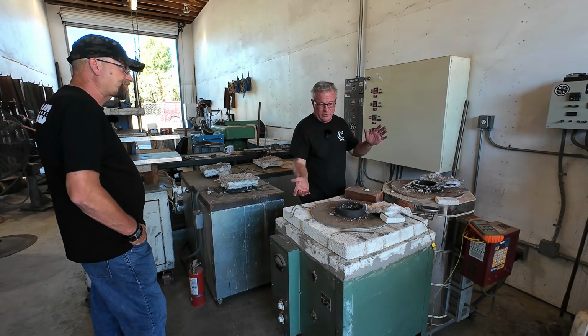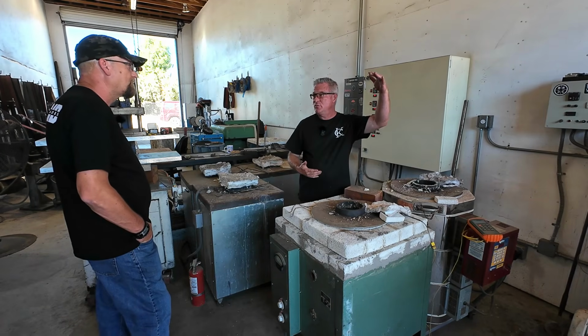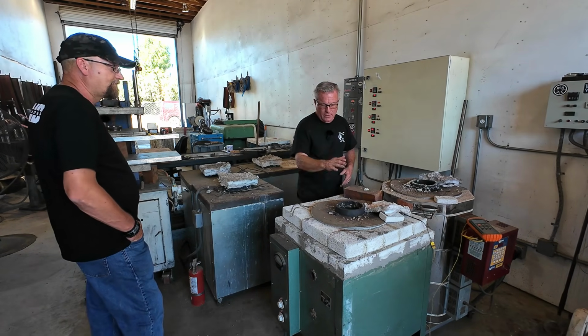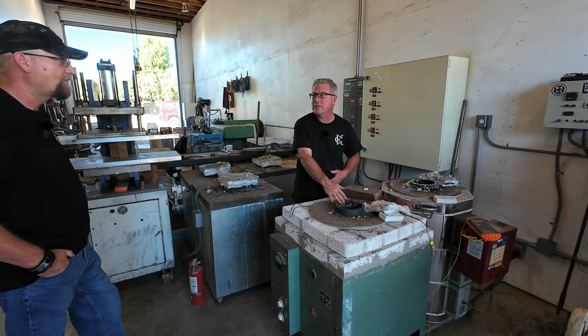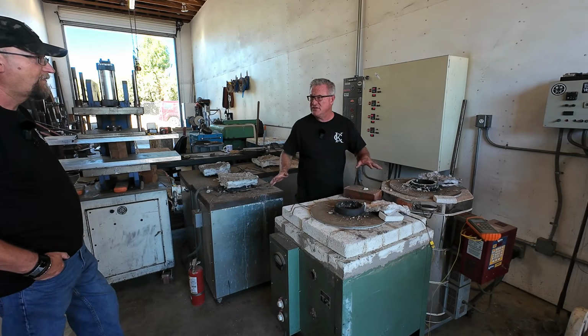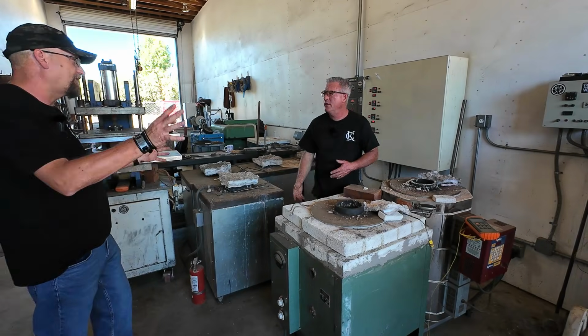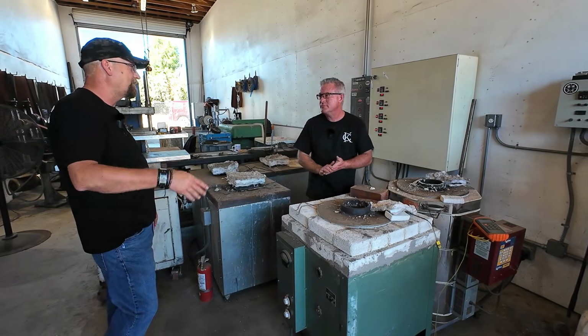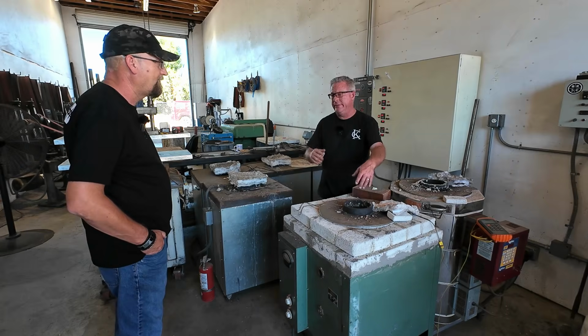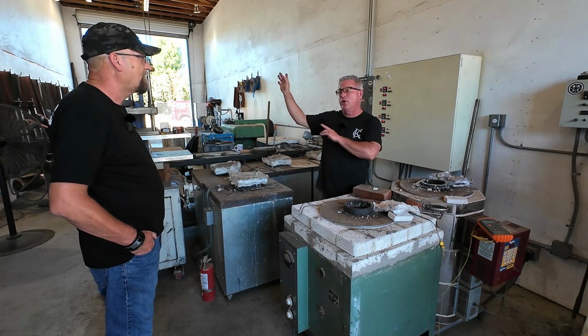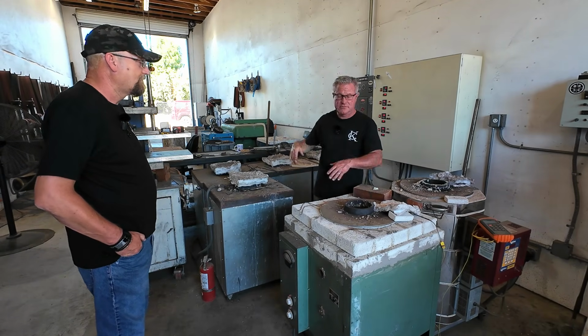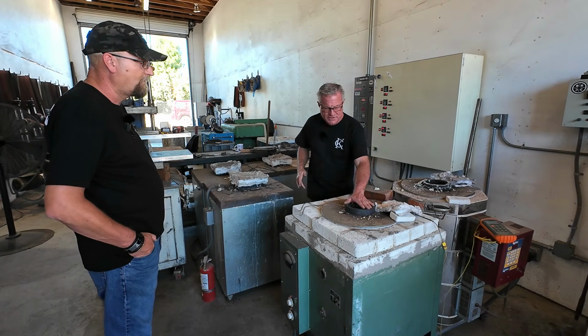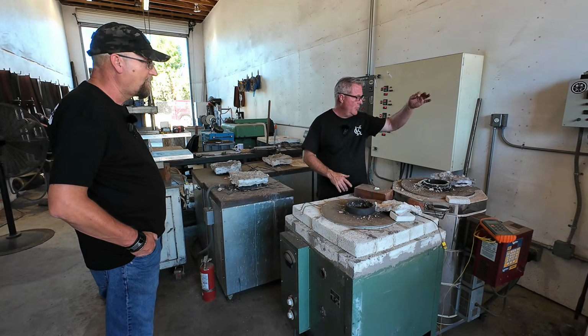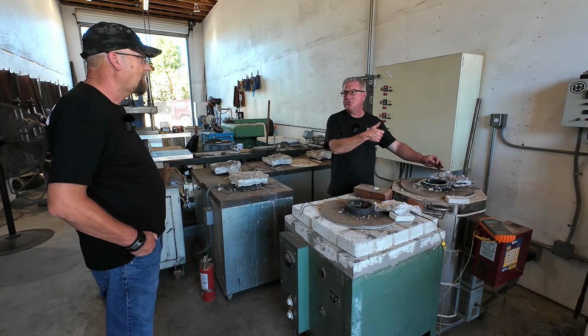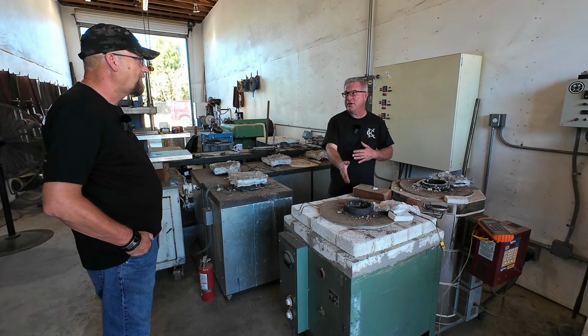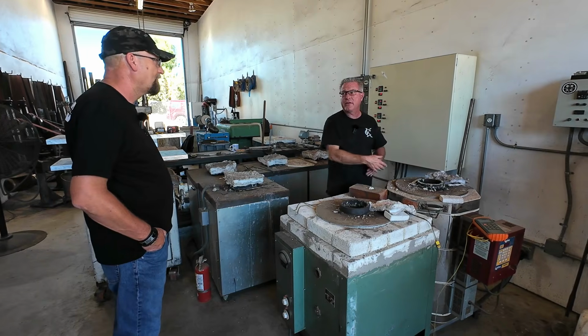This I use if I'm doing stainless steel, which needs higher temperatures to harden. I'll use this as a preheat. So you've got a preheat that helps de-stress the steel, and you get up to the normalization in your ramp up. Exactly. It's in here for who knows how long because you're not into that hardening zone, you're not in that austenitizing zone. So it's sitting here at 1500. Put it in here, and it's at 2000 right now because it's already hot, so you're not putting a cold blade into that.